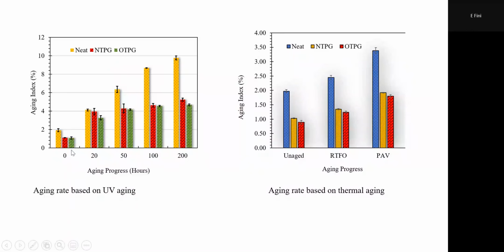test is important. In this scenario, we actually did aging index, one based on thermal aging and one based on UV aging. So the one on the left here is when we put the samples, each one of these asphalt samples having different plastic, under intense UV aging. We aged it for 200 hours under UV. And as you can see, the aging index is going up. The yellow here is neat, and you can see after 200 hours compared to 0 hours, the yellow one is going sharply up.